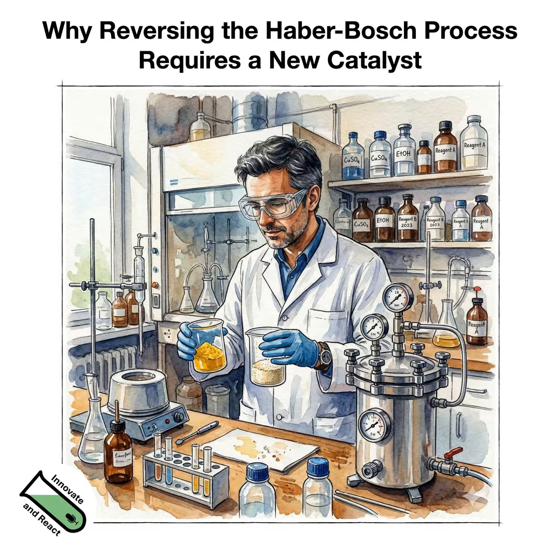It was studied a lot, mostly also because of the whole field of model catalysis, which typically finds it not easy to implement the high pressures that you need for ammonia synthesis. They contributed a lot to fundamental mechanistic work on ammonia, but mostly by looking at the formal reverse reaction, because the conditions were just not right in order to conduct ammonia synthesis. So it's possible. We have a catalyst, but we may need better ones.